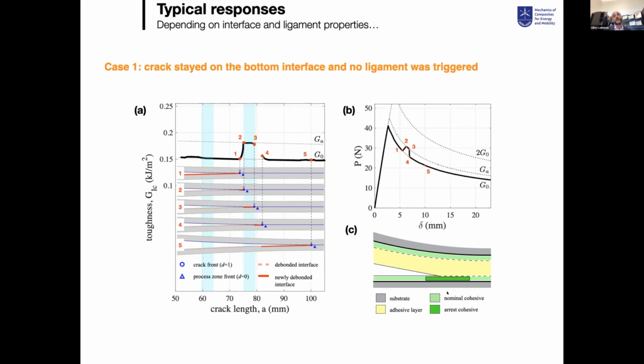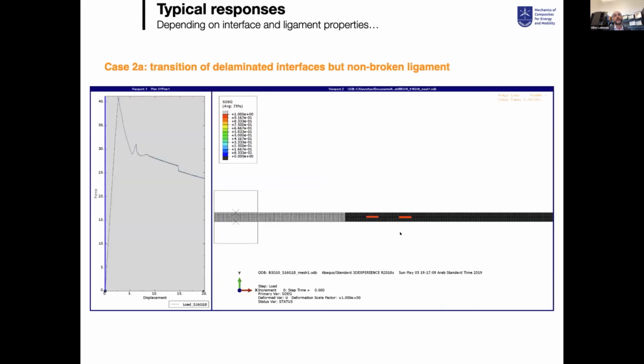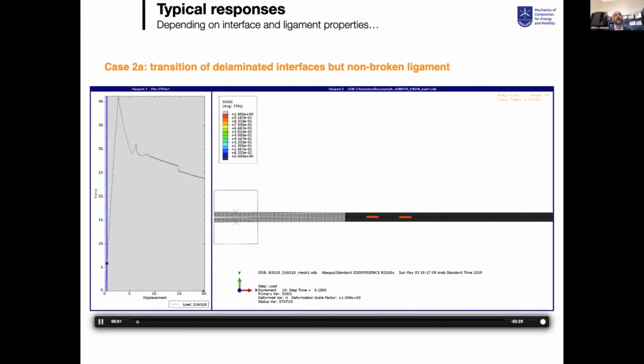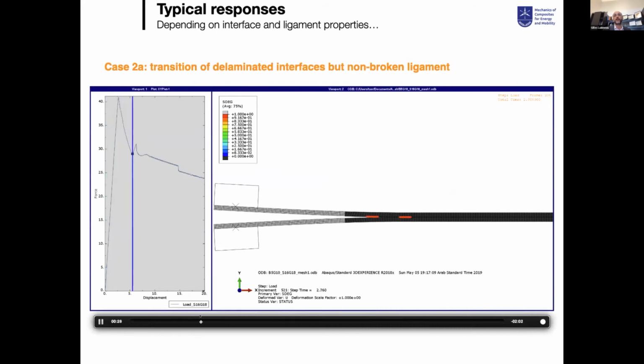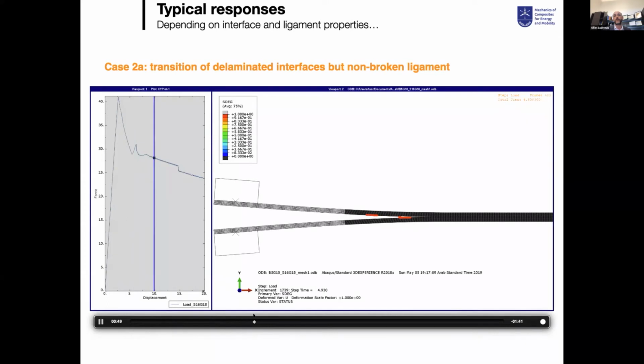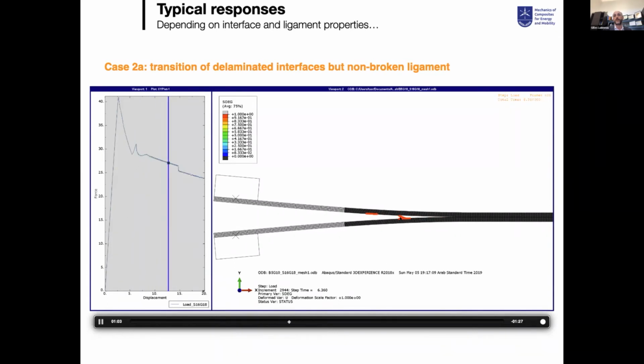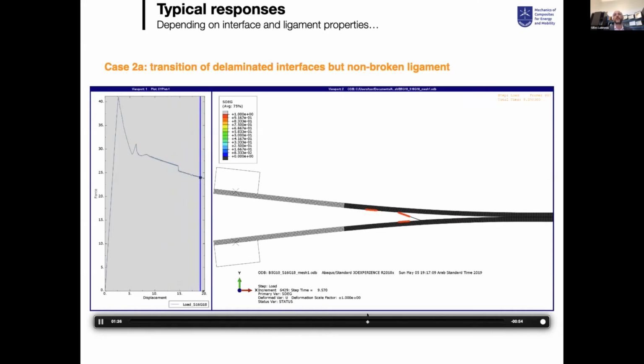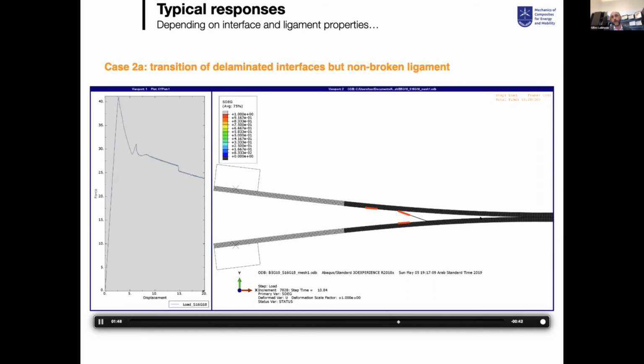Now, what is interesting is that when you start to play with the contrast, you start to introduce what you call bifurcation. That means that your crack is propagating at the bottom, and then at some point the crack gets pinned on the bottom here due to the contrast in properties, and you are going to initiate a secondary crack in the top. That means you are going to be able to initiate a ligament, and your adhesive bond line here will create a ligament between the bottom substrate and the top substrate. And instead of having a single crack propagation, in fact, you will have three crack propagation, one on the bottom here, one at the end here, and one on the back face on the top here.